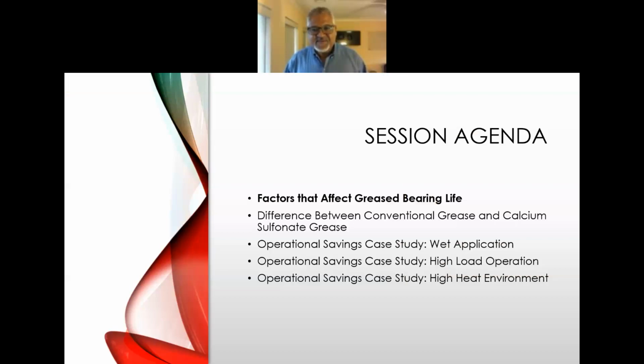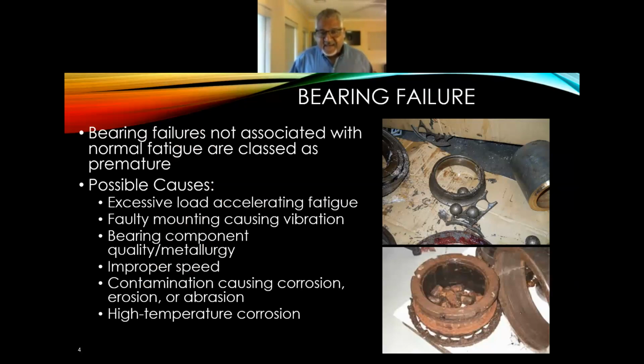Let's talk about factors that affect grease bearing life. Bearing failures not associated with normal fatigue are what I want to classify as premature. Possible causes are excessive load, accelerating the fatigue of the bearings, faulty mounting of the bearing causing vibration, accelerating wear and fatigue. Bearing components, maybe the wrong metallurgy or the wrong quality of manufacturing may be involved. Improper speeds. If the bearing is run too slow or too high of a load, or too fast, generating too much heat, maybe the speed does not match with the base oil viscosity of the grease or the lubricant. Contamination that may cause corrosion or excessive erosion or wear, abrasion.